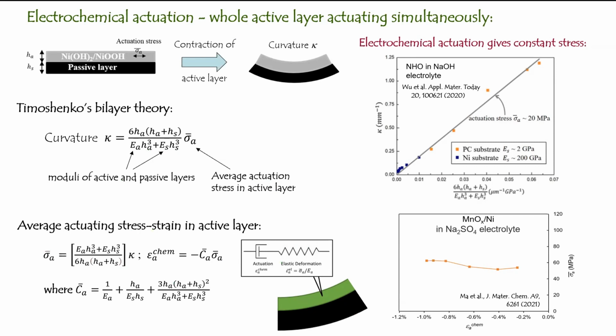So for electrochemical actuation, these are the experiment results. The experimental curvature is plotted as a function of this factor, because we can produce different actuators using different materials and also different thicknesses, so that factor can be varied. Then we observe a pretty straight line. In this case, the active layer is fixed to be this NHO system. That means that the NHO system in the sodium hydroxide electrolyte can give an actuating stress, which is given by this slope, around 20 megapascal. Not bad already. That 20 megapascal is many times compared to our human muscle.